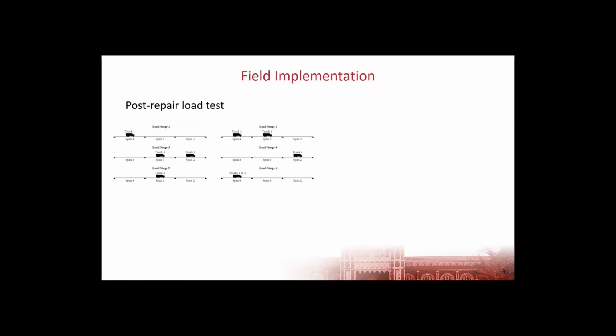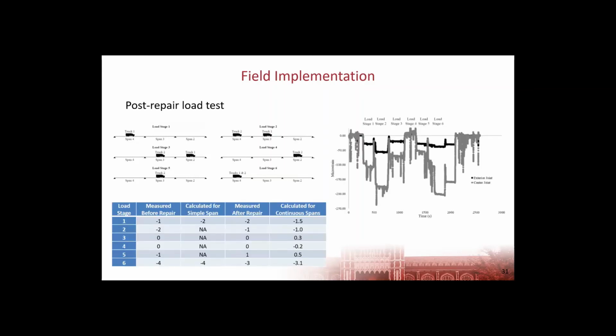All right, so just quickly looking at the post-repair load tests, we used 6 different loading stages to characterize all the different possibilities for continuous behavior. And if we look at both measured before and after, as well as calculated for assumed simple spans before and continuous spans after, we see all the signs that we're getting the continuous type behavior that we anticipate.